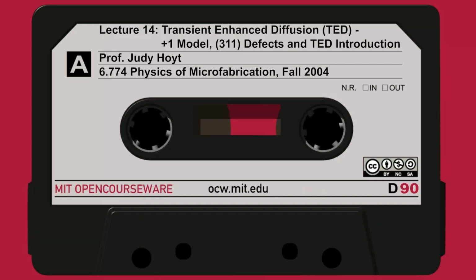And so this is a relatively efficient way to do dopant activation. I'll say a little bit more about dopant activation in this lecture. And finally, we mentioned last time, we just started this topic, that the excess interstitials created by this implant, all these nuclear collisions, can cluster into a particular type of defect called a 3-1-1 defect. Later, these 3-1-1s dissolve and give off interstitials, and these interstitials are what determine the kinetics of transient enhanced diffusion of boron and other dopants.